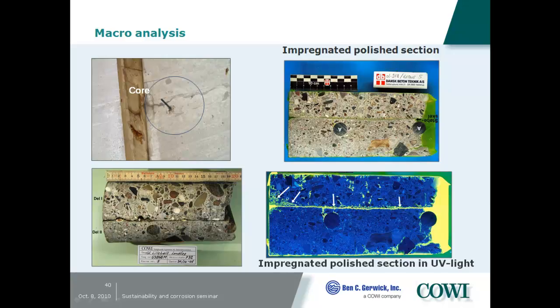And what you can see here is this is a reinforcement, and you have the cold construction joint here. And if you look at it under UV light, we can be very happy about the concrete cover in this direction, but we have hardly any cover here. And also we had not a very good casting around the reinforcement. So then it did not in many cases take much for corrosion to take on at that place.